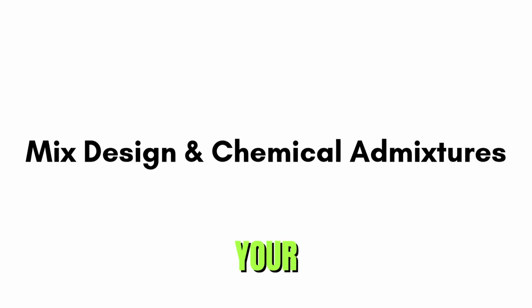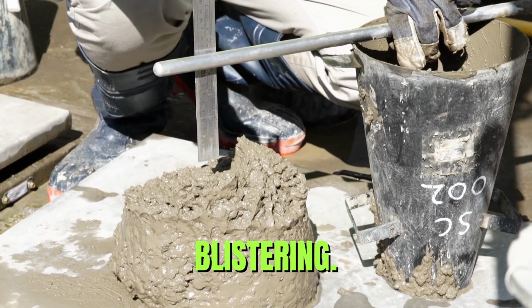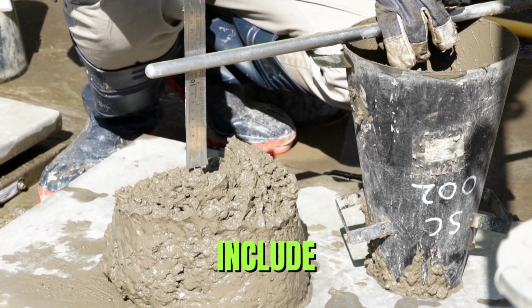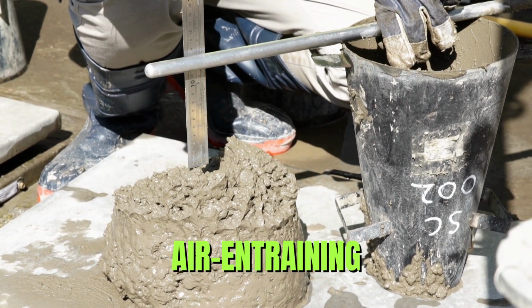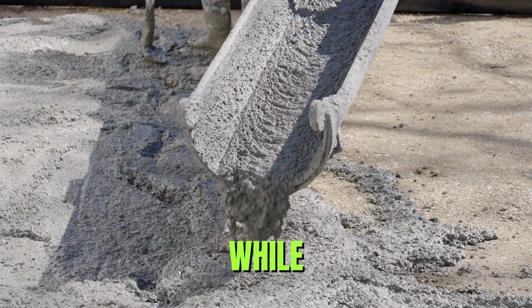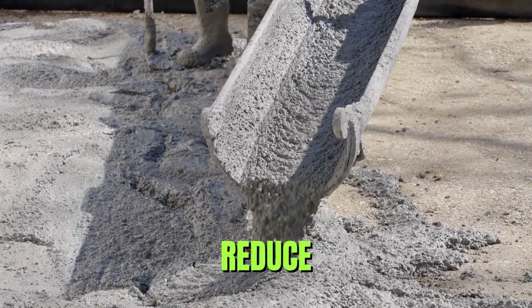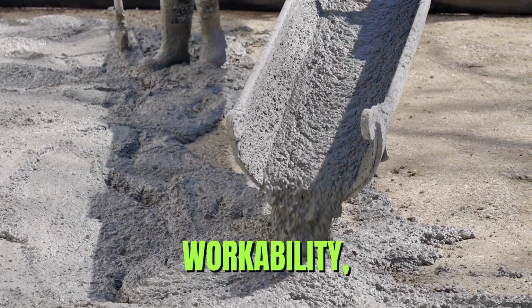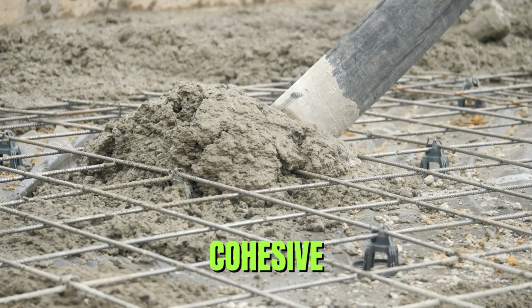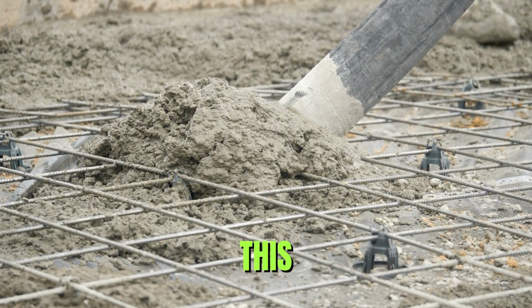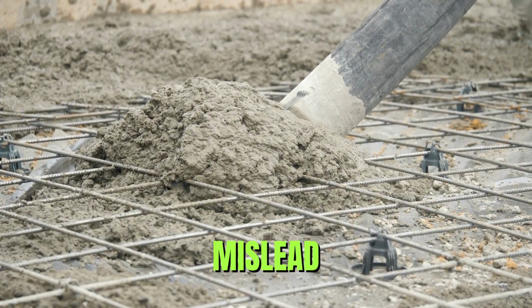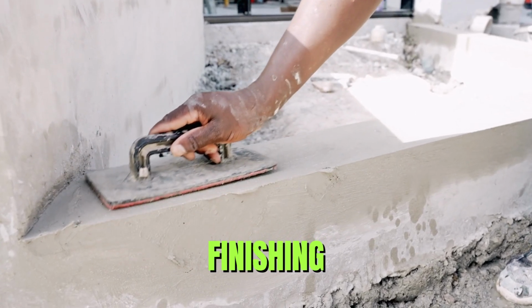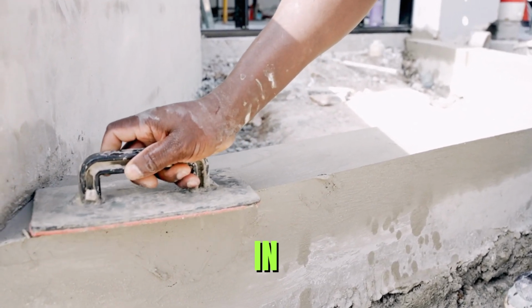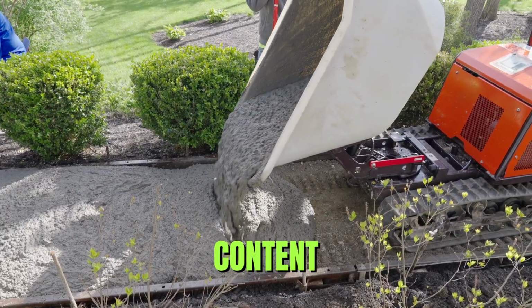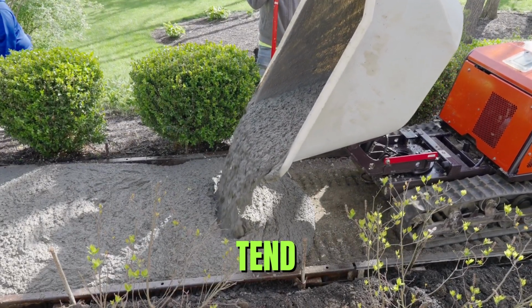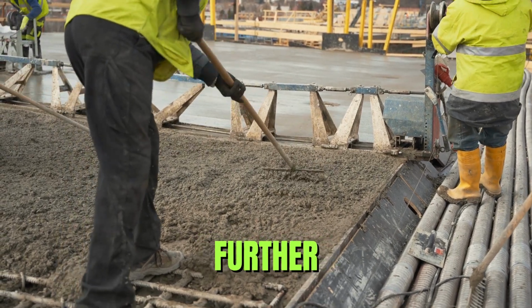Concrete mix design is your first line of defense against blistering. High-performance mixes often include chemical admixtures, such as air entraining agents or silica fume. While these enhance durability and reduce permeability, they also alter workability, making the concrete more cohesive or sticky. This reduced bleeding rate can mislead finishing crews into initiating finishing operations too early. In addition, mixes with high cement content or increased fines tend to seal quickly under troweling, further increasing the risk of entrapped air.